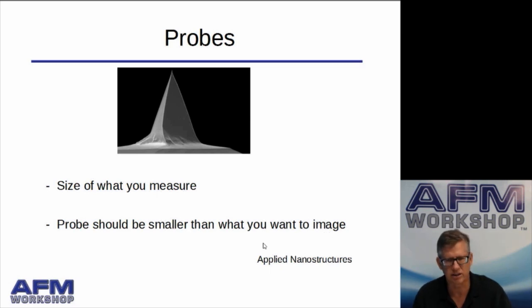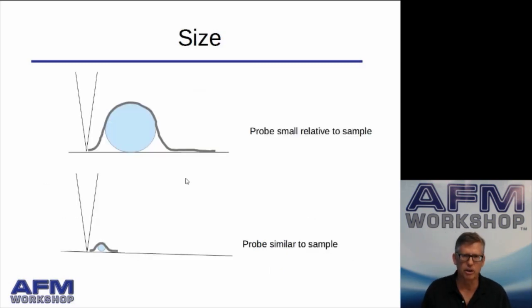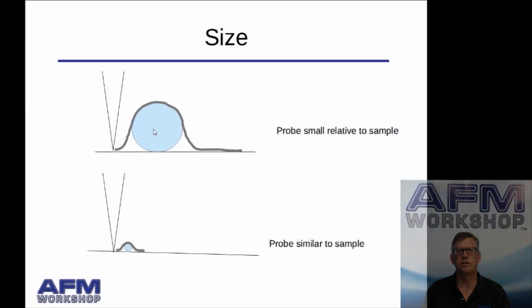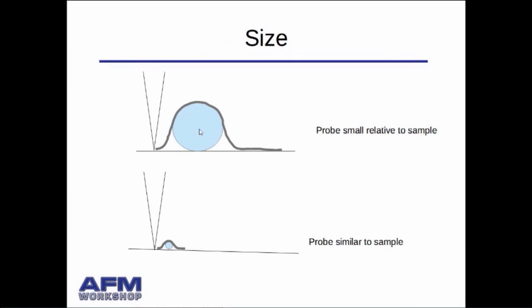I have here on the next slide the example of a probe going over a nanoparticle. And there's two things that you'll note here. The first is that no matter how sharp the probe is, you'll get the correct measurement for the height of the nanoparticle. And this is general for a lot of atomic force microscope measurements: when you're measuring heights, that's the vertical dimension, the probe geometry is not so important. However, if you're measuring the width of it, it's quite important.